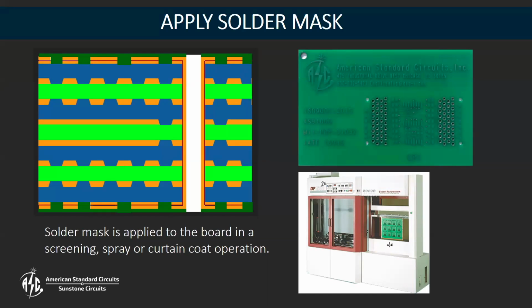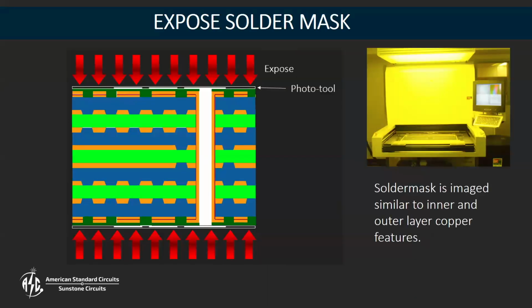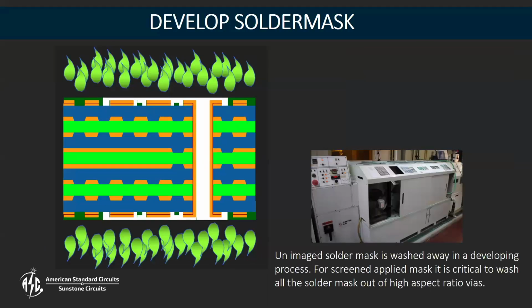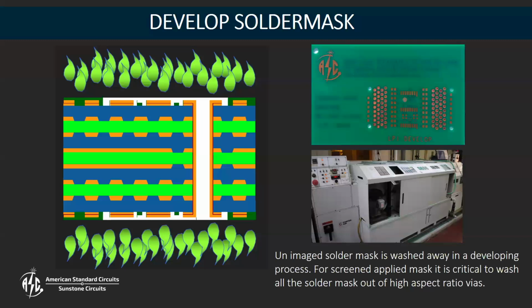So we're going to apply that solder mask layer to the external layers. We flood coat it over everything. So all of the copper solderable features are covered at this point, but then we go through an exposure process again, very similar to what we have at the inner layers and the outer layers stage. And we are going to develop off solder mask and expose those solderable surfaces. All right, so we can see some of the via holes are still covered with solder mask by design. But our solderable features, our pads and through holes, etc., are now void of the solder mask layer.